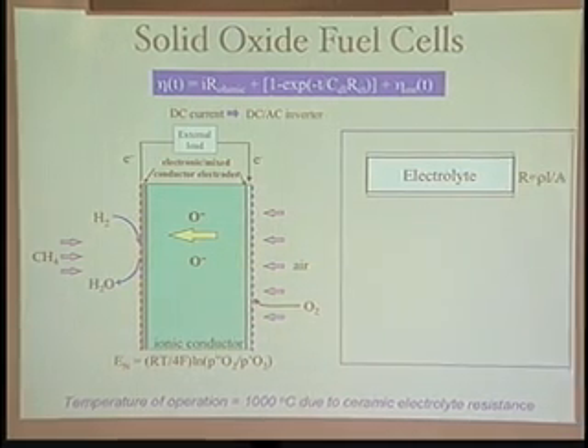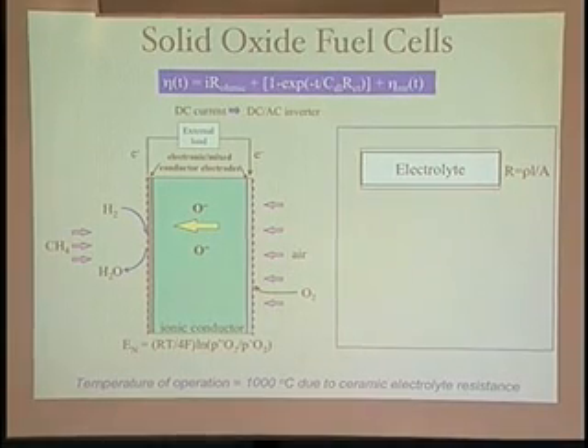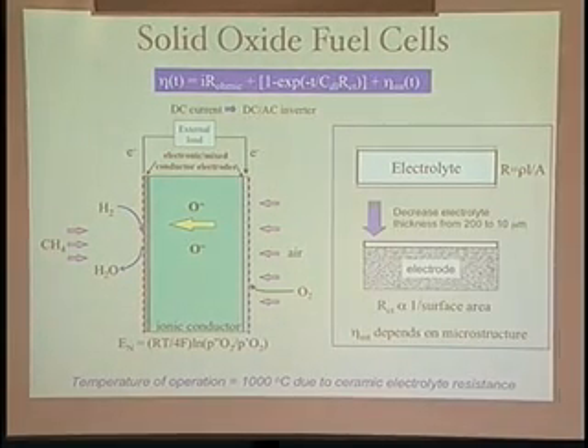If we start with something like this, with a thick electrolyte with thin electrodes that are screen printed on, we can kind of reconfigure that. So now instead of having this thick ceramic plate, why don't we just have a very thin plate? It's a very simple idea, because if you do that, the resistance is directly proportional. So if we go from 200 microns to 10 microns, the resistive drop across here gets a lot lower. And we could run this thing at 800 centigrade now. And you can start to think about metals. And maybe we can go even lower. And so what happens when you do that? Well, the IR term gets better, and the electrode resistance decreases because this goes as a surface area.